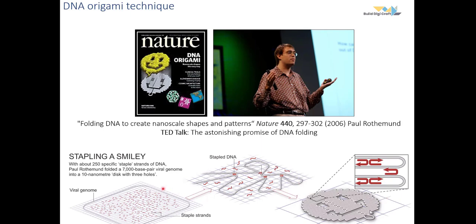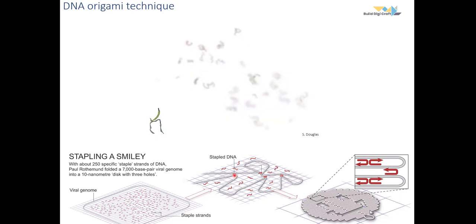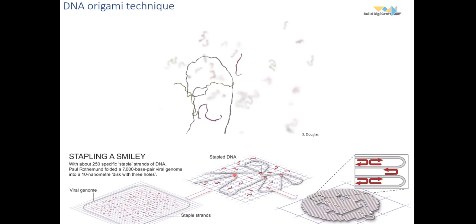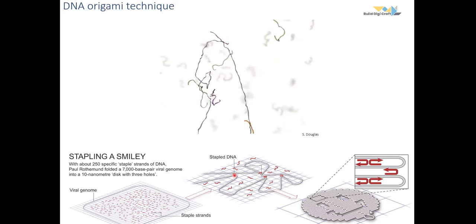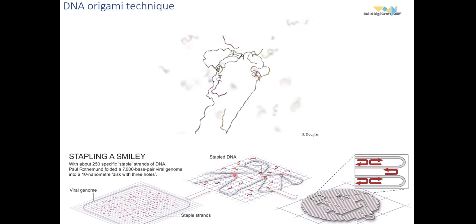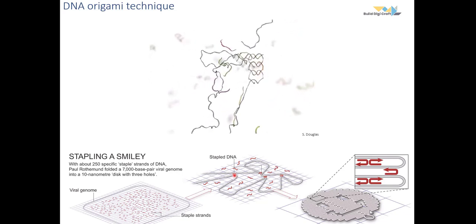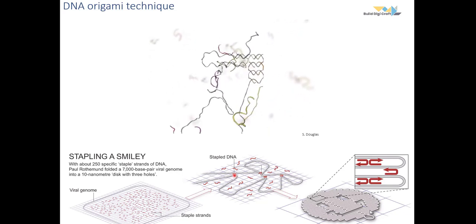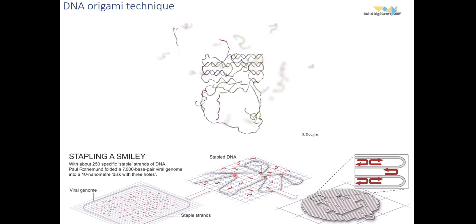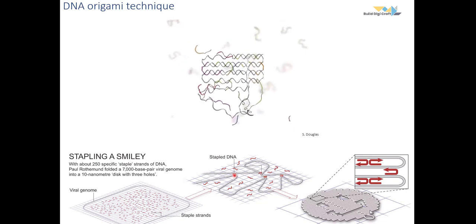Yeah, and it combines this long strand and around 200 short synthetic DNA strands together. So that's how the process works. You take your DNA strands, you mix them together, you add some salts, you heat your solution up, and as you cool them down, these DNA strands will come together, bind into the places they should bind, and then form the structure which you wish them to form.